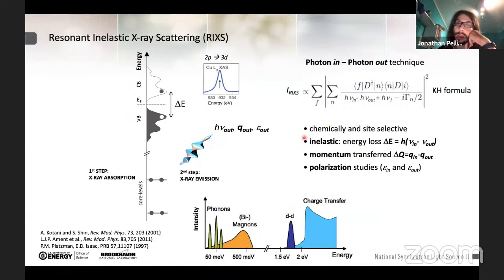This is an inelastic process, so we can investigate all of the excitations that are accessible as a function of energy loss. Additionally, an advantage over optical spectroscopies is that we can transfer momentum, because normally we work in the soft or hard X-rays, and the energies of these X-rays are high enough that they can carry momentum. And such a momentum can be exchanged with the system. Finally, a bit more technical, there is the possibility of performing polarization investigation. So we can selectively tune the incident polarization in order to select different orbital states or even different magnetic states.